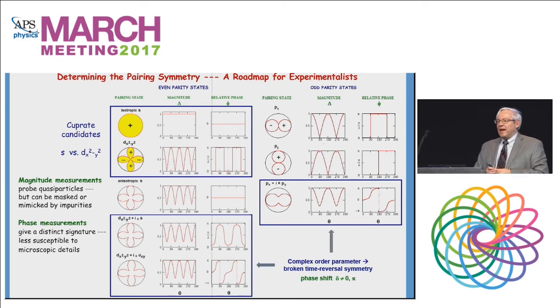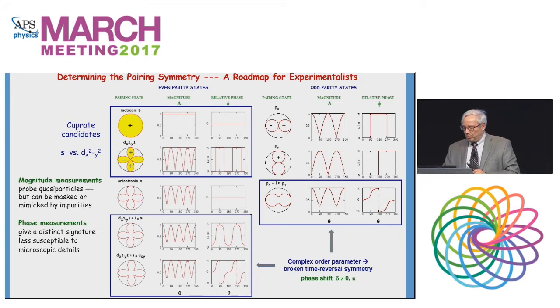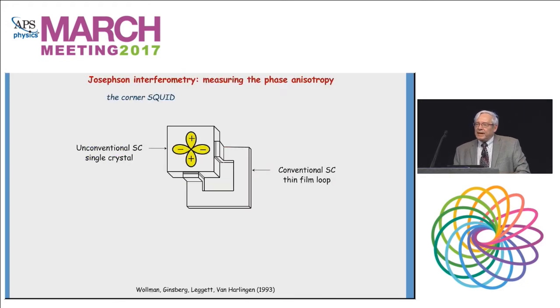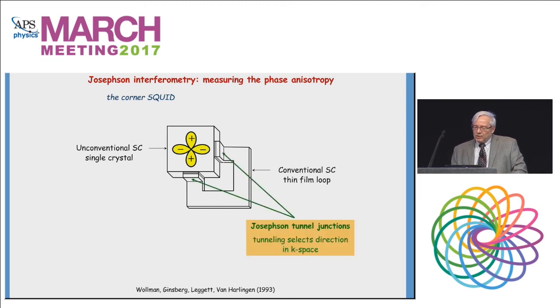At that time, the two main candidate states were S-wave superconductivity and D-wave superconductivity. The big difference is in whether there was a phase variation in the order parameter. So the technique we came up with, actually suggested to us by Tony Leggett, is really simple. It's an interferometer. You measure the phase the way you always do in superconductors, in quantum materials. You put Josephson junctions on a crystal in two different orthogonal directions. Those probe the directionality. Because they're directional, they probe the k-space direction in different directions.